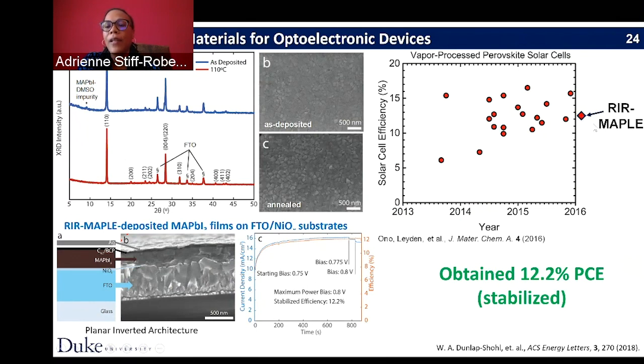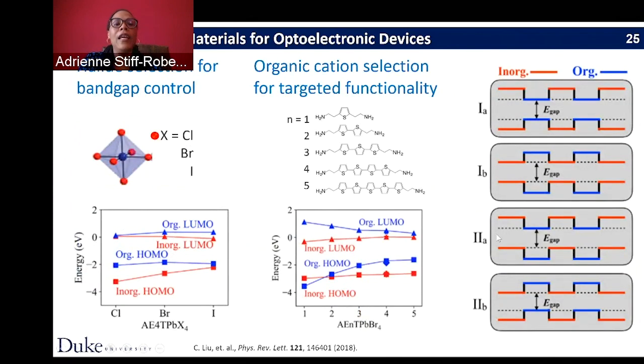So this data is a little bit outdated, but at the time that this was demonstrated, you can see that this MAPLE film that we didn't spend a whole lot of time optimizing was still giving us device efficiencies very comparable to other approaches for vapor process perovskite solar cells, and we got a stabilized power conversion efficiency of 12.2%. But again, that's not really the interesting problem. The more interesting problem is when we start to take that small organic molecule and replace it with a larger one.